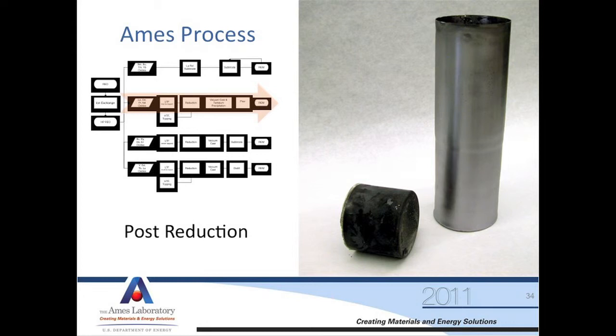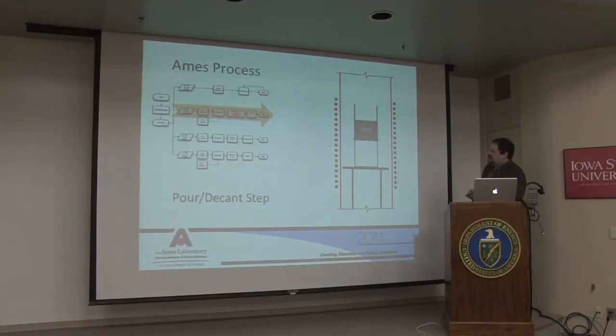If it doesn't come out nicely, you literally have to get a foot-long chisel and chisel it out by hand, and it takes you a long time. And you can't be very aggressive with the chiseling because you don't want to damage your crucible while you're doing it. When we've done the vacuum casting, then we'll do the pouring.